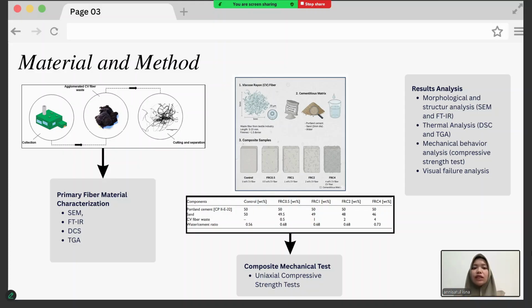The mixtures were molded into cylinders, 100 millimeters in height and 50 millimeters in diameter, cured in water at 21 degrees Celsius, and tested after 7, 14, and 28 days using an axial compressive strength test. The analysis includes morphological observation, thermal analysis, mechanical strength measurement, and visual failure evaluation after testing. Next.